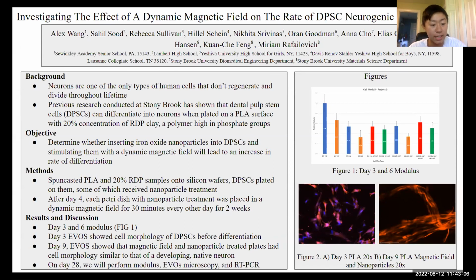We also performed 2 EVOS testings throughout this process, one on day 3 before the neuronal media change and on day 9 after. And what we see on day 9 is on the exact same sort of surface, polylactic acid, there's a high morphology similarity to native neurons. So you could see on the photo on the right compared to the one on the left, there's like tubular development of neurons, axonal development, and eventually we're hoping to see some dendritic development as well to show that we have the morphology of a native neuron.